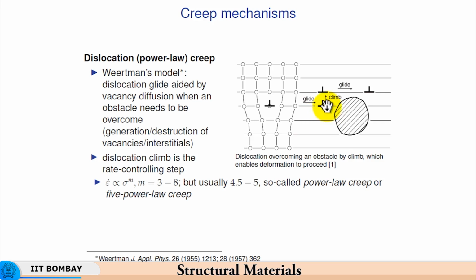But that requires much more stress, that requires a much bigger path, whereas here, because of temperature, the climb becomes easier, and then on a new plane the dislocation glides without any hindrance. So, that is how the strain rate is facilitated by the dislocation climb. If you want resistance to be built, then this dislocation climb will be counterproductive, because at high temperatures this climb would be very easy.